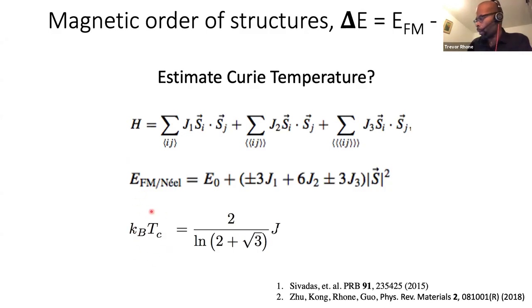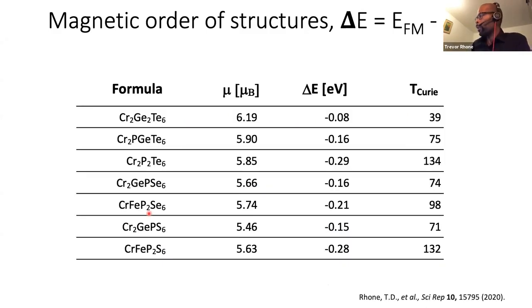Okay. And if we do that, we can compare the Curie temperature of our predictions with that of chromium germanium telluride. It turned out that at 39 Kelvin or so, our prediction is close to what people actually measured in experiments. Okay. The key point here is that by making atomic substitutions, you can increase the Curie temperature up to 134 Kelvin for chromium phosphorus telluride.